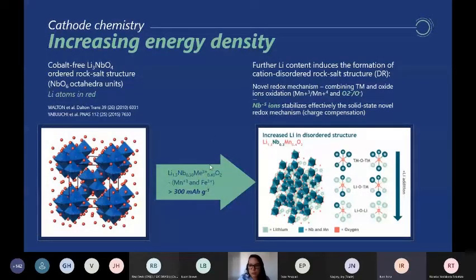We can see this in this figure. This modification can favor the lithium diffusion in the structure and increase the energy capacity. The high energy capacity in this material is attributed to the combination of the transition metal and the oxide ions oxidation in parallel reactions.